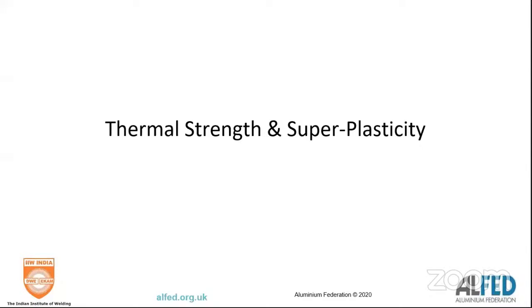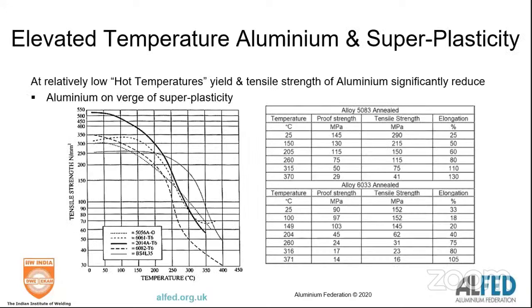Moving on a bit more. One of the most important properties of aluminium is that at relatively low temperature, its yield and tensile strengths dramatically reduce and it becomes super plastic. Most aluminium alloys at about 100 degrees C will have lost about 10% of their yield and tensile strength. By the time you're at 400, 500 degrees C, bearing in mind it's got a low melting point, you might be down as low as 10% or 15% of the yield and tensile strength. It becomes super plastic, and the forces to deform aluminium become very, very low.